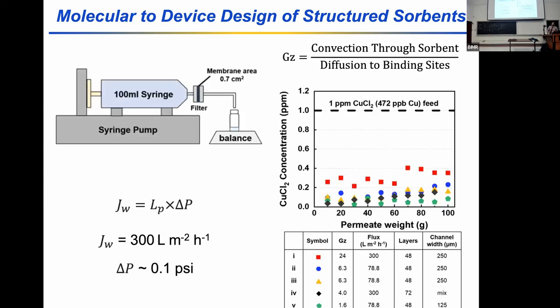And then we could go ahead and do a breakthrough curve again. And now we begin to see that we want to design these a little bit more intelligently. We want to think about what is the channel distance and reduce the channel thickness, or sorry, the channel diameter, and increase the membrane thickness. We see that our breakthrough curve shifts further and further down because we're giving the molecules enough time to be captured. And so there's some real room for engineering these at both the nanostructure scale as well as the micrometer and millimeter structure scale, but it's an encouraging first result.